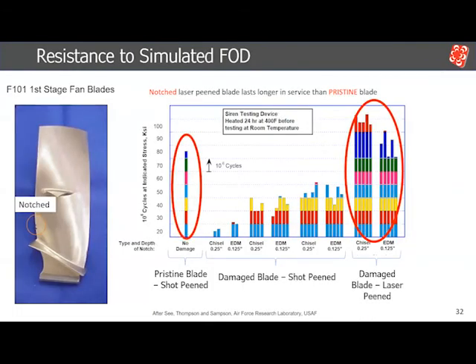Okay, so let's go a step back. I did explain the improvement that we got from the foreign object damage, but I didn't explain how we got that improvement. In a simple way of looking at it, foreign object damage is nothing more than notching your blade. So what does a notch do? It's a location of high stress intensity factor. So it's the weak point where a lot of the cracks are going to initiate and propagate.